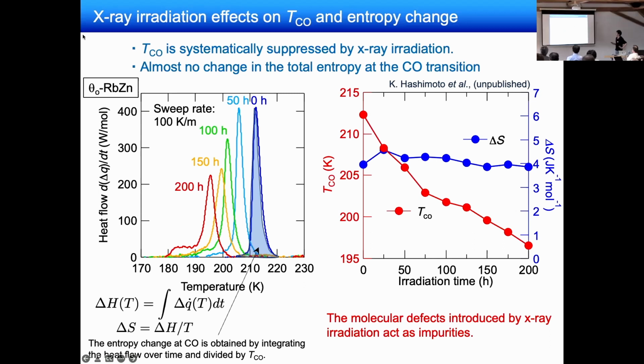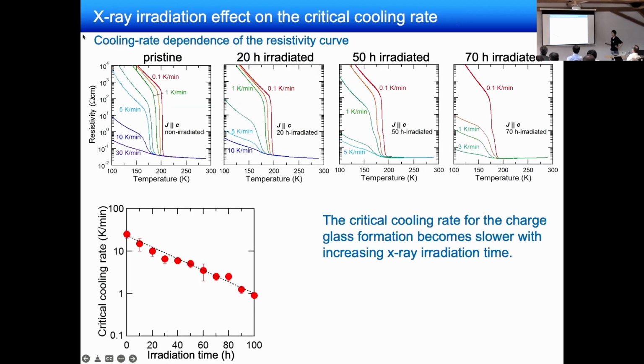Okay. Then we measure the resistivity. We measure the temperature dependence of the resistivity for each sample with different irradiation time. And as you can see, the critical cooling rate for the charge glass formation becomes slower with increasing X-ray irradiation time. For the pristine sample, the critical cooling rate was 30 Kelvin per minute, but now it becomes 1 Kelvin per minute for 100-hour irradiation.